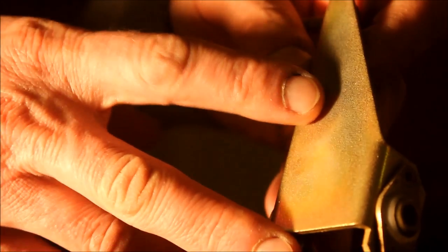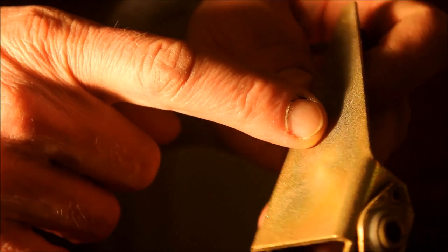But if you have rough, granular looking deposits like this, that's caused by your current density being too high. The surface feels like a Brillo pad. Now, if the whole part's affected by that, it's just your current's too high. So go back and check your area calculations and the current that you're using and redo it. If you've just got a local bit like that, you can either just live with it as we're doing here, because these are just functional parts, or if the finish is really important, you can sand it back lightly before passivating and it will improve it no end.